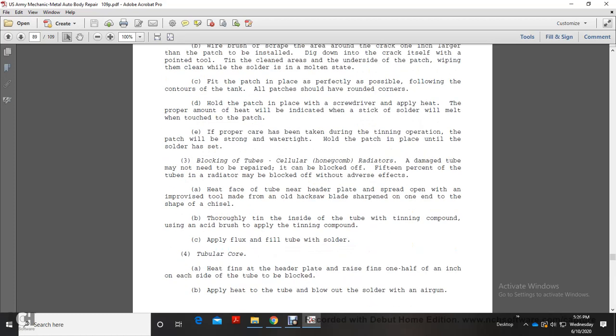Blocking the tubes. In cellular honeycomb radiators, a damaged tube that may not be repaired can be blocked off. Up to 15% of the tubes of the radiator may be blocked off without adverse effect. Heat the face of the tube with the header plate, and spread the fins open with an improvised tool made from an old hacksaw blade sharpened at one end in the shape of a chisel.